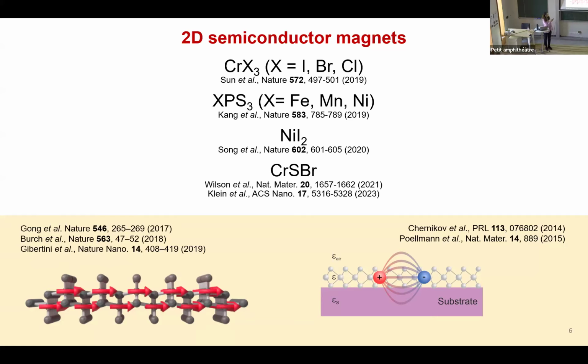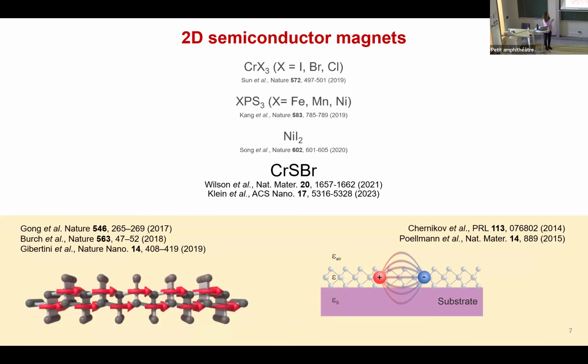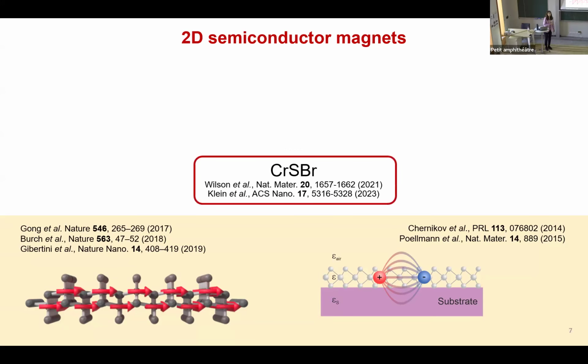Today, I will focus on a specific category of van der Waals magnets, which is chromium sulfide bromide. Chromium sulfide bromide has attracted a lot of attention because, as you will see, it has relatively high magnetic phase transition temperatures. And on the other hand, it remains air stable down to the monolayer. This is not a trivial property for many metallic or semiconducting van der Waals magnets that have been discovered to date.